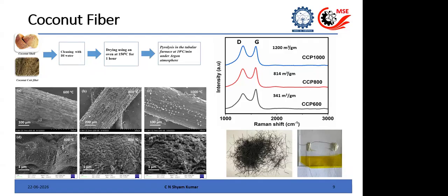So we took that and did a pyrolysis, just heated it until 1000 degrees Celsius in an inert atmosphere, argon or nitrogen. What you can see is that as the temperature increases, the morphology remains the same, because you still get carbon fibers, and you can actually connect those things. So the morphology remains the same.